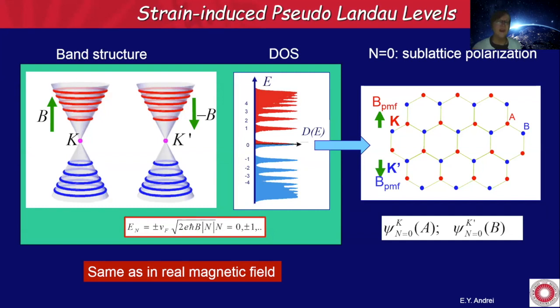Now, there's something very special about the n equals 0 level here that sits at the Dirac point. It has a so-called sublattice polarization. What do I mean by that? And this is true whether you apply a real magnetic field or a pseudomagnetic field. What I mean is the wave function in the K valley sits uniquely on the red sublattice, the A sublattice, and the wave function in the K prime valley sits uniquely on the other sublattice.